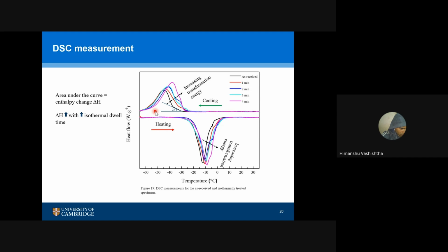However, the area under the curve is what we call enthalpy of transformation. So we are cooling it. If you remember from my earlier slides, during cooling we go either to the martensitic or R phase, from the austenitic phase. So here the austenitic phase will be there, and as we cool it, it's transforming to martensite. The area under the curve is called the enthalpy change to form austenite to martensite.